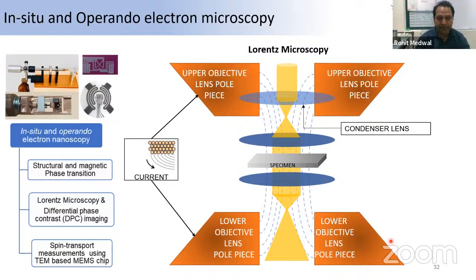So I would like to give a very basic example or explanation. What is this Lorentz microscopy? Basically, in the TEM, we use the objective lens to focus the beam. This is the electron beam. We focus on the specimen using the electromagnetic field. So we use a normal solenoid coil to focus this beam on the sample. And if we are working on a magnetic sample, it's difficult to do the measurements because the field which we are using in the TEM is 2 Tesla. It will saturate most of the ferromagnetic materials. So it's impossible to do this type of measurement in the TEM.